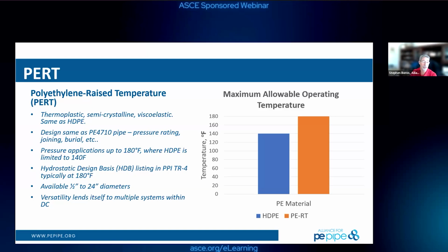So each letter or each number has a meaning. Within the standardization system, ASTM D3350, the 4 means it's high density. The 7 means it's of extremely high slow crack growth resistance. And the 10 is the stress rating of the material in units of 100 PSI. So essentially it has a 1,000 PSI long-term hoop stress rating. That's what all the standards today require to be used for municipal piping applications and industrial piping, FM certified material, firewater systems, all use PE 4710 grade materials today, and they're readily available. The highest level performing, it's really the 4th generation of pressure piping materials for polyethylene.